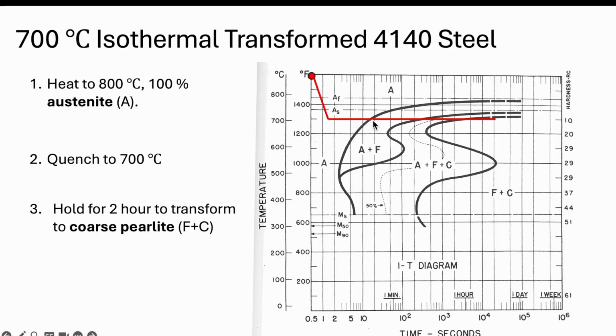So that means that ferrite's going to form. So that is ferrite in the structure. So ferrite plus austenite. And then we keep going, and you'll see that it takes a while in this case. So we're at about 2 minutes now, where we start to cross this line. So this is where we have austenite plus ferrite plus cementite. So here we just formed ferrite, and here is where we're forming perlite. And so that reaction takes quite a bit of time. And so you can see down here at about an hour or so, we've potentially reached full 100% of that structure becoming perlite. So we have ferrite plus perlite.